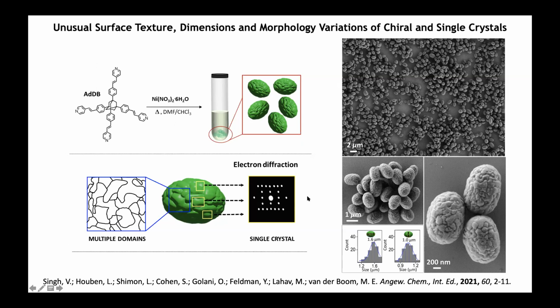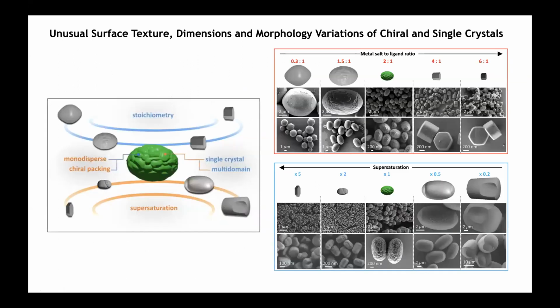Sidney Cohen did a lot of AFM work on these surfaces, but also Lothar Houben did a lot of electron diffraction measurements on this, and also Linda Simon worked on that. And we came to the conclusion that it's indeed a single crystal and not some weird polycrystalline material. So when you have such a system, you try to beat the hell out of it. You try to figure out what is going on. You try to see what will happen if you change, for instance, the metal salt to ligand ratio. You try to change concentrations and so on. Whatever we throw at this system, the uniformity remains very high, as shown here to the right. You see the beautiful structures here with a high level of uniformity.